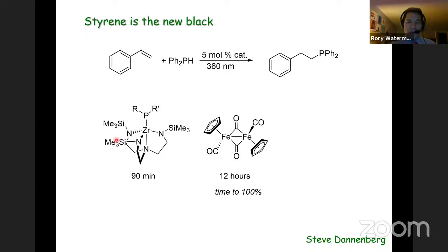So for zirconium derivatives, under 360 nanometer irradiation, within 90 minutes or less, for the secondary phosphine, we see complete conversion into the hydrophosphination product. The Fp dimer I mentioned a couple of minutes ago takes about half a day to go to about 100%. And that's really a function of generating enough of the 17 electron intermediate. For the zirconium, it's really a function of how many photons that compound will absorb at that wavelength. These are clearly relatively fast compared to some of the conventional systems.